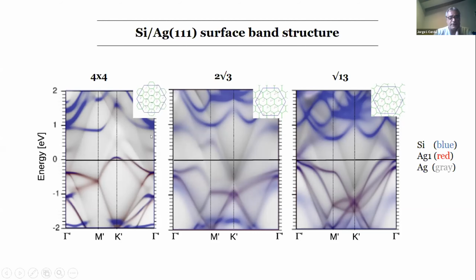Anyhow, you can see that none of the three phases shows any Dirac cone at all, as could be expected from the previous works. We can see a strong hybridization between silver and silicon close to the Fermi level in all the bands. The unoccupied part is more silicon type, but as I say, we can rule out any Diracness on this surface.